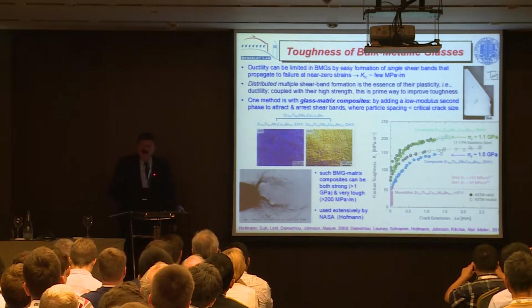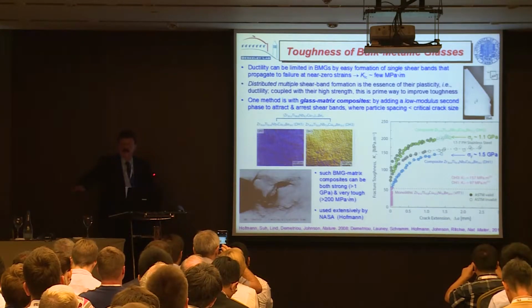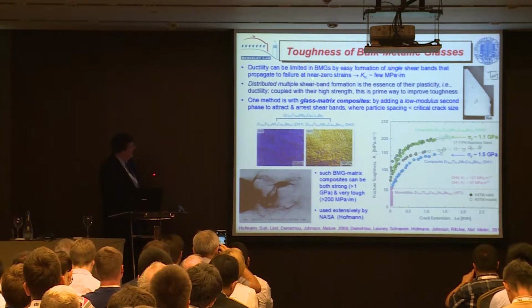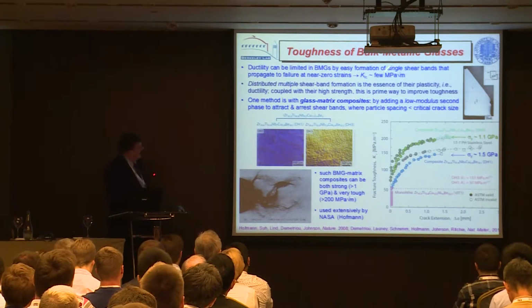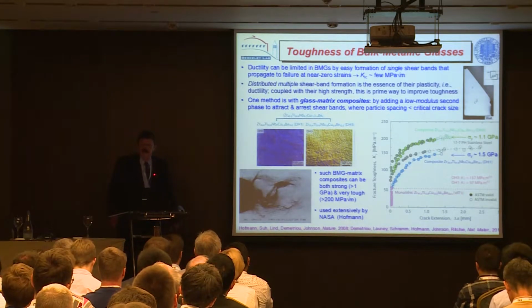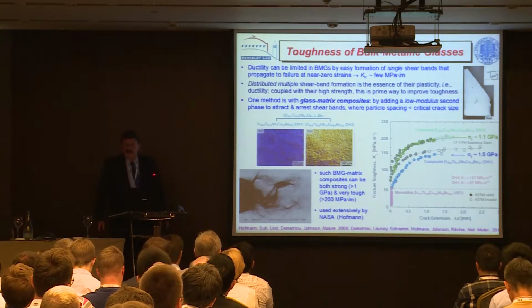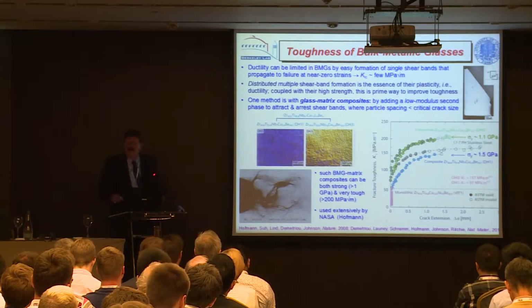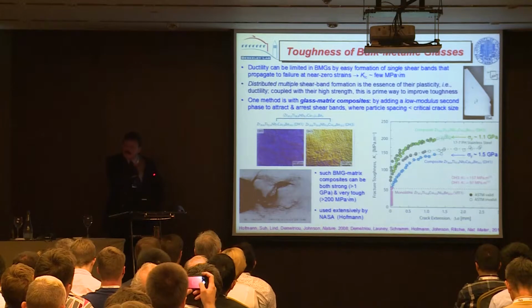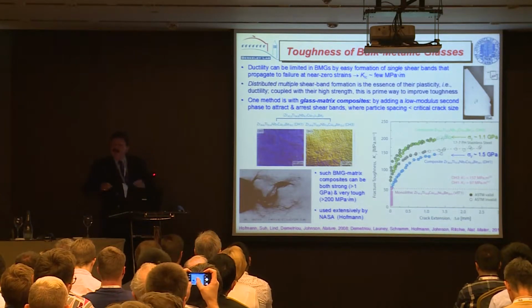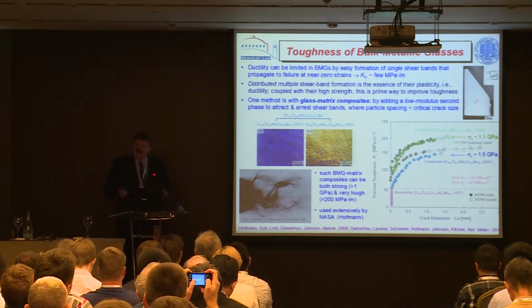and in many glasses, you form a single shear band, it zips across the material, the thing fails at near zero strains, and the toughness is down to 1 or 2 megapascal root meters. So that is obviously not a good thing. But it turns out that if you can distribute and have multiple shear bands, this is the basis of plasticity in these materials. So a single shear band will kill you, but multiple shear bands gives you plasticity.